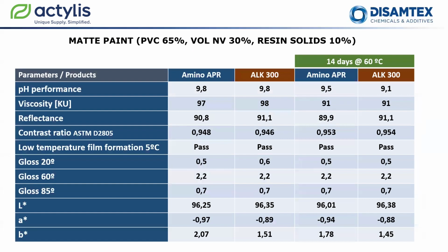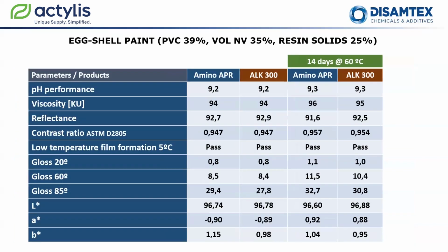For this type of paint, under time 0, and a second evaluation after 2 weeks' time at 60 degrees Celsius, indicating an accelerated simulation compared to the real world, what was seen was a slight drop or equivalence of numbers. We can say that, yes. This means our product performs in a very stable way over a long period of time, say 1 year plus. Same with an eggshell kind of paint.